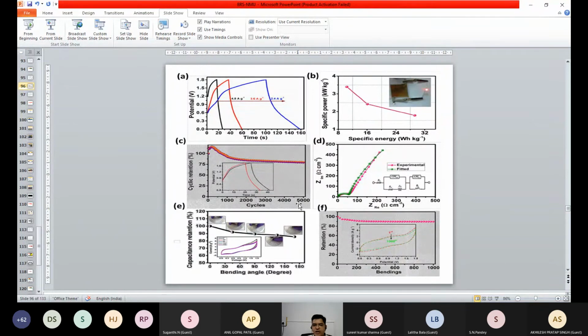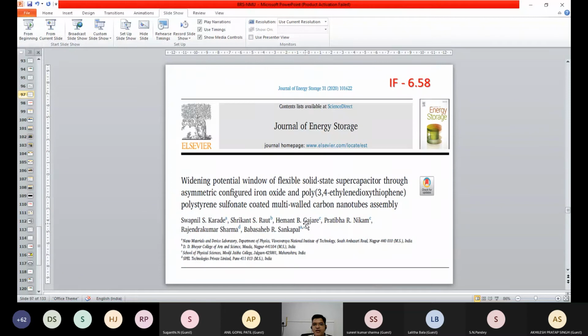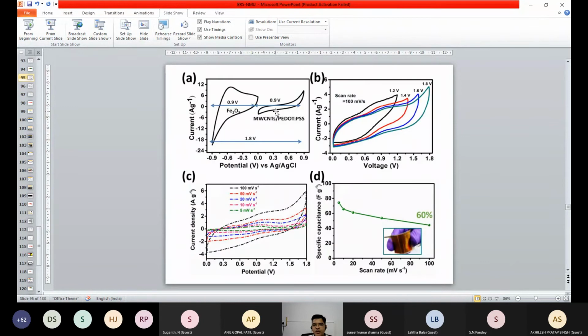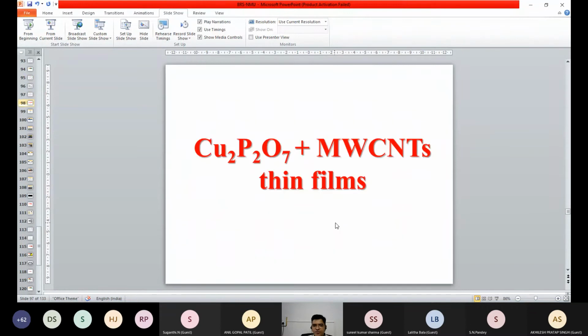So it is completely flexible, and for 5000 cycles, it gives 75% stability, right? This is with respect to the bending angle. This is with respect to the number of bendings. So one time bending, two time bending, up to 1000 times bending. So it is very, very stable. Whatever Fe2O3 and carbon nanotube coated with the polymer, the device shows very high stability. And that is the beauty of it. This was published in the Journal of Energy Storage with an impact factor above 6. The title was about widening of the potential window. Because of the addition of these two things, the potential window is enhanced to 1.8 volt. That was our target, and it was published in this journal.